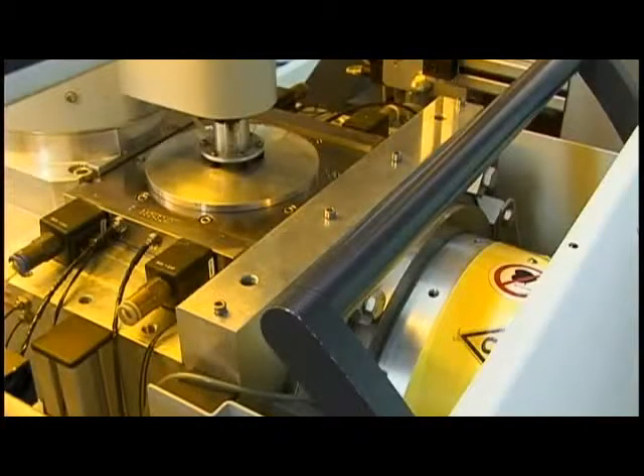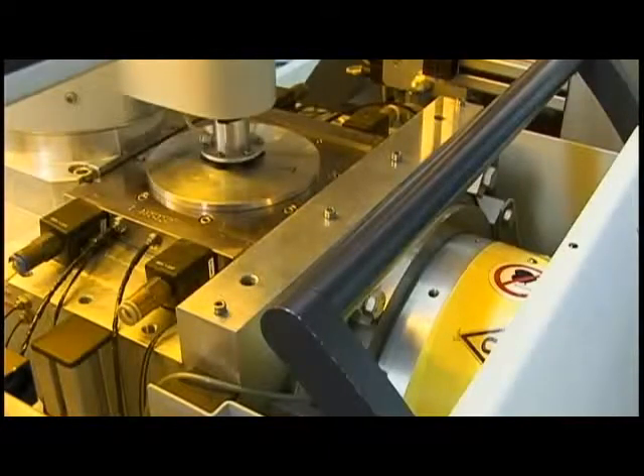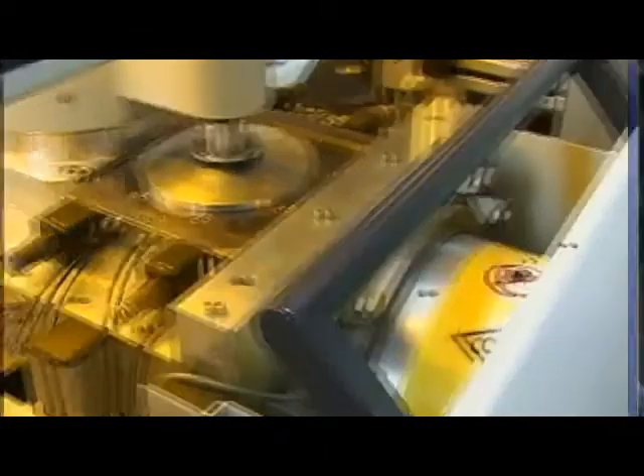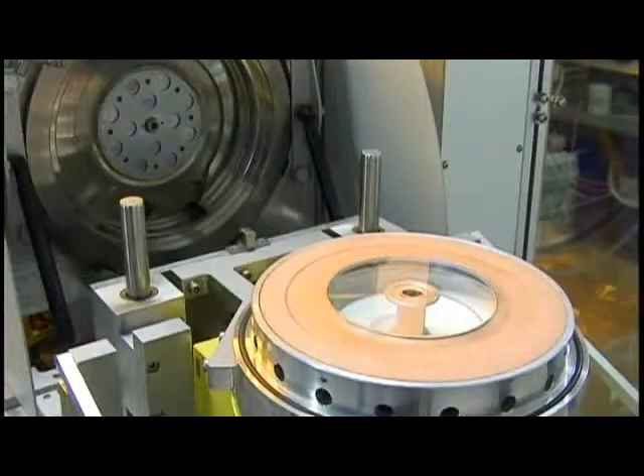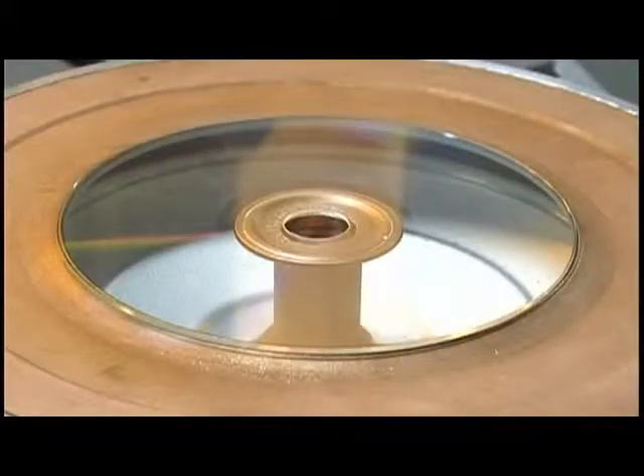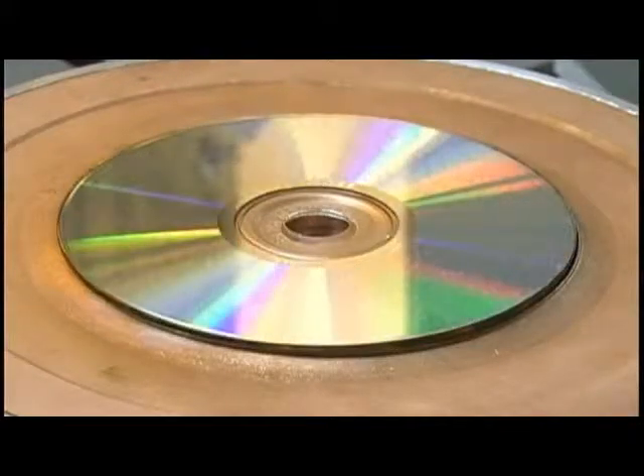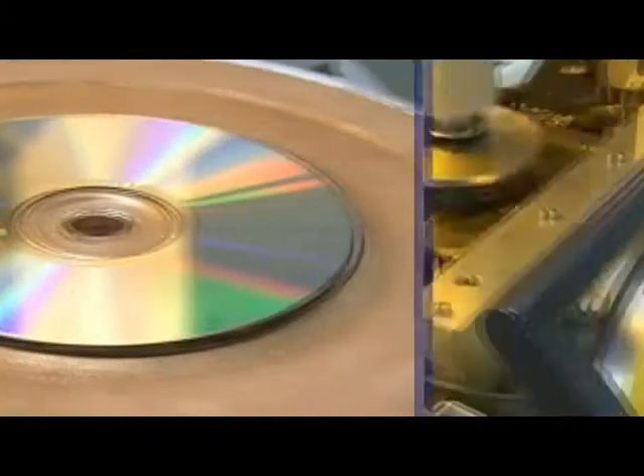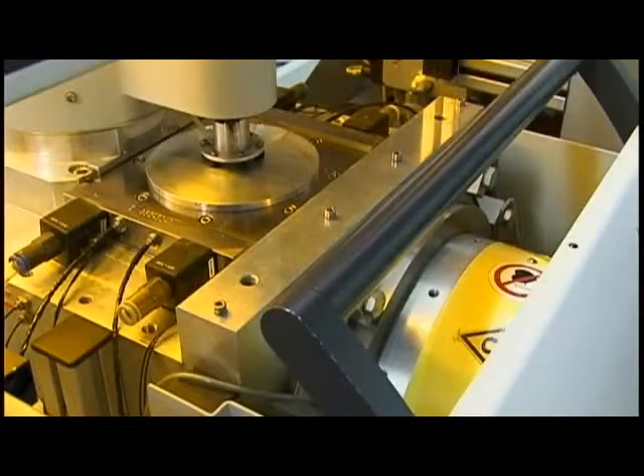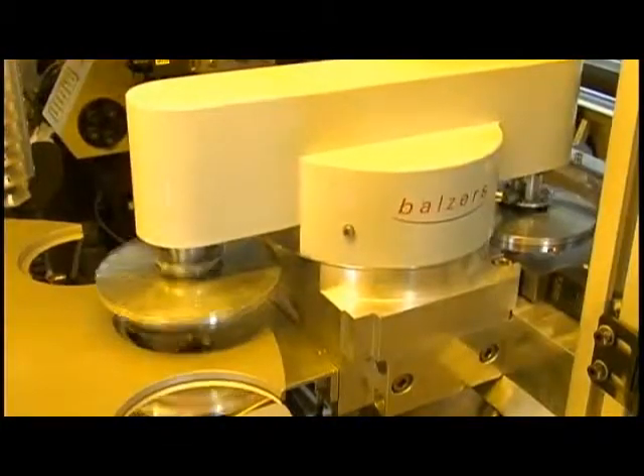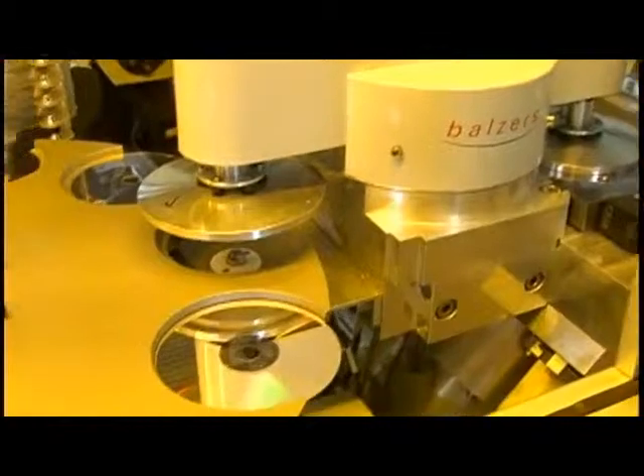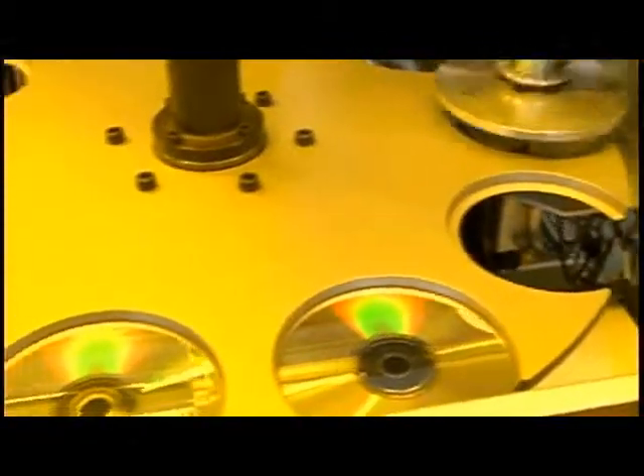Metallizing is done in a vacuum chamber. The process used to metallize the disc is called cathode sputtering. It is a process that is used to produce thin films. Ion bombardment removes particles of coating material from a target, and these particles are deposited and settle on the disc. After the metallization process is complete, which takes about 2 seconds, the swivel arm moves back and deposits the disc back onto the round table.